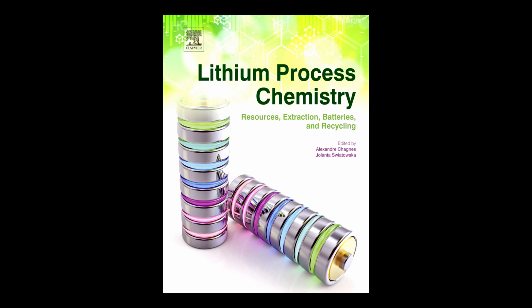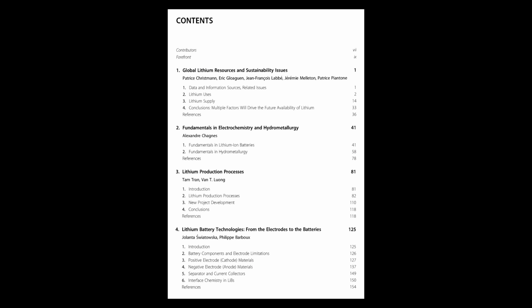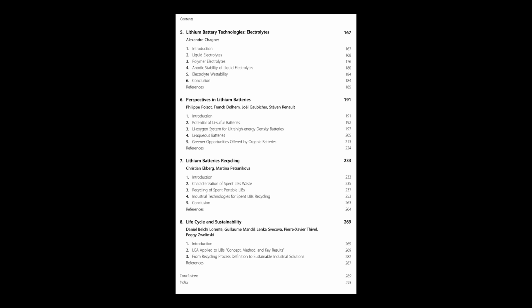Yeah, that's a thin layer that forms on the anode surface, especially graphite, during the first few charge cycles. It's actually formed by controlled reaction with the electrolyte. So it uses up a little bit of lithium and electrolyte initially. It does, which is a downside. But a stable SEI layer is essential. It acts like a protective film, preventing further uncontrolled reactions between the anode and the electrolyte later on. It's crucial for long cycle life. Figure 4.1 probably shows these voltage limits visually. Okay, interesting trade-off there. Then Section 3.